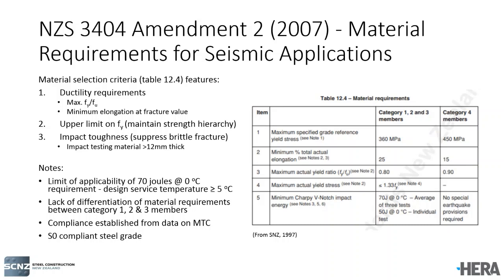In 2007, Amendment 2, there were new material selection for seismic application criteria introduced. These are found in table 12.4, and they feature ductility requirements. So there was a maximum Fy over Fu of 0.8 value. There was a minimum percentage of elongation at fracture of 25%. There's also an upper limit on the maximum yield stress on the test certificate.